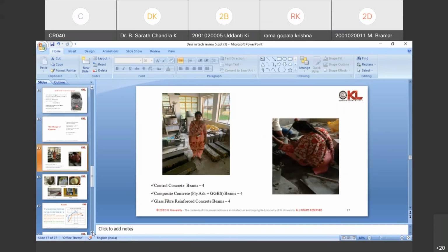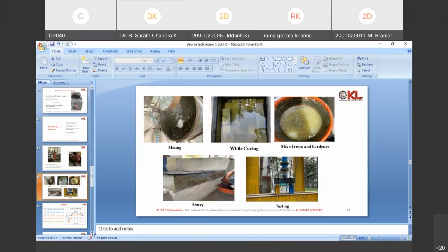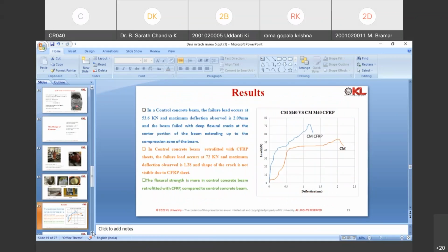These are my beams while casting. Mixing while curing, mix of resin and hardener, applying epoxy to the beam, and testing in loading frame. Results. In the control concrete beam, the failure load occurs at 53.6 kilonewtons and maximum deflection observed is 2.09 mm. The beam failed with a deep flexural crack at the center position of the beam, extending up to the compressive zone of the beam.